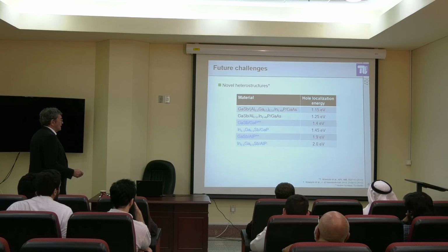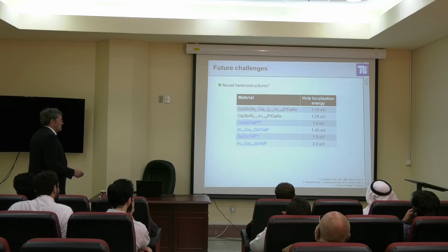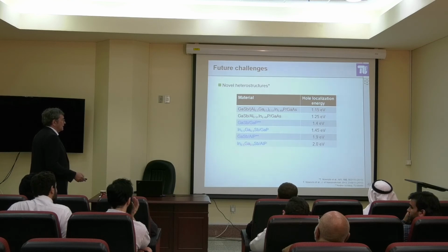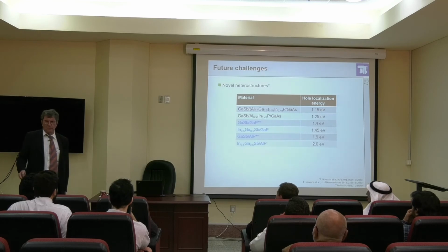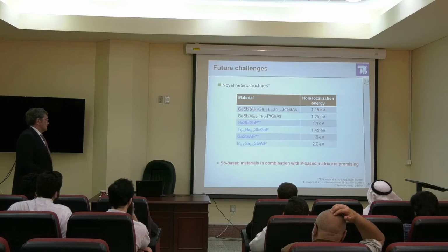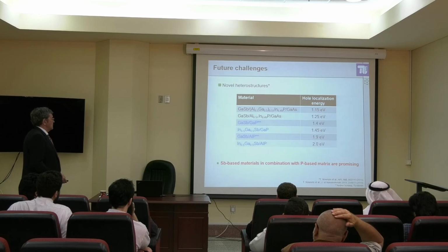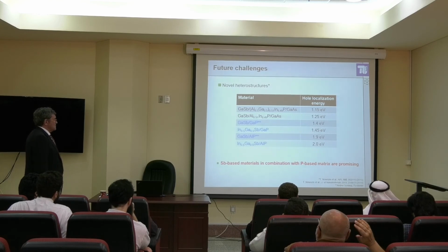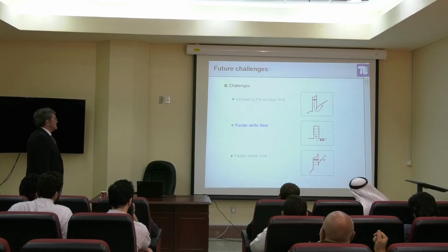1.4, so we replace the gallium by 50% indium. We don't gain so much. It's not worth the effort, but that is worth the effort: indium gallium antimonide. So we are ending up here, and that's enough, definitely, whatever the capture cross-section is. So antimony-based materials in combination with a P-based matrix are promising.